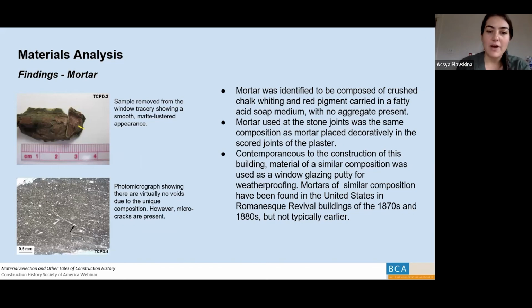In the mortar, we also found something very interesting regarding the timeline of installation. We found that the composition of the original pointing mortar was crushed chalk whiting and red pigment in a fatty acid soap medium, and there was no aggregate present in this mortar. This was very unlike typical 19th century mortars. When we looked at the mortar installed in the scored plaster joints, we were very surprised to find that it was the same mortar composition as that of the tracery joints, which were load bearing, and the column joints. It was very interesting that they chose to install true mortar into those plaster scored joints, which is really a finish layer.